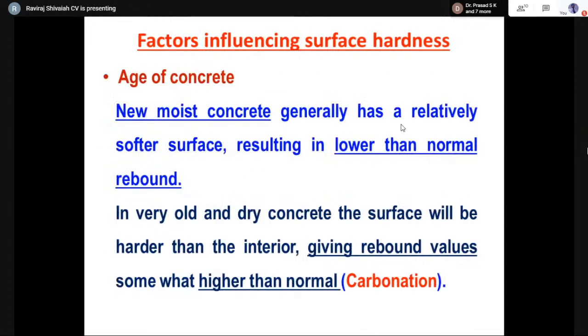And it's important to understand that when we do the test, you have to record the age of the concrete. For example, if it's very new, moist concrete, the surface is relatively soft, and if you take a rebound number, since it has not hardened completely, you will see that the rebound numbers are less. And there could be some depressions seen on the surface. On the other hand, if you take a rebound on a very old and dry concrete surface, there is a possibility that the concrete surface is much harder than the interior, giving rebound numbers somewhat higher than what we are supposed to get.